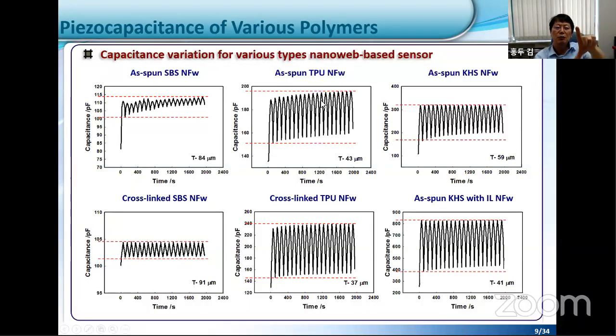That's each time I press it and release, the value slowly increases. That means it doesn't recover back to the original distance. But in the case of KHS, the capacitance value at the press state gives us a very constant value. That means it's very elastic. Although it takes more time to release, when we release it, the capacitance value goes back to the original location, so it has a slight creep behavior, but it's not that serious. And then we tried to improve the sensitivity of this material.